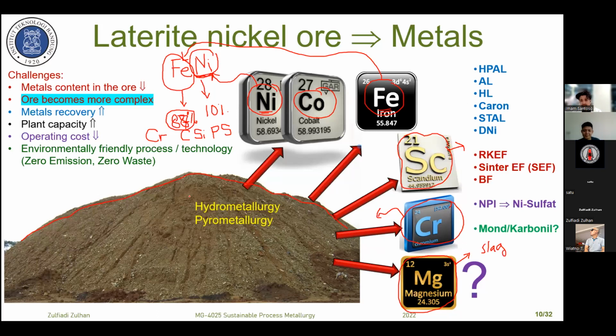If you look at the valuable metals in the nickel ore, for sure nickel is number one, or cobalt is actually number one because it is expensive, but the content of cobalt is less compared to nickel. So we can say nickel is number one and cobalt is number two. But iron, nobody buys the iron. It is challenging for us to recover scandium in the ore, and also to recover magnesium, when it is possible to extract the magnesium from the ore. For us as metallurgists, it is a challenge.